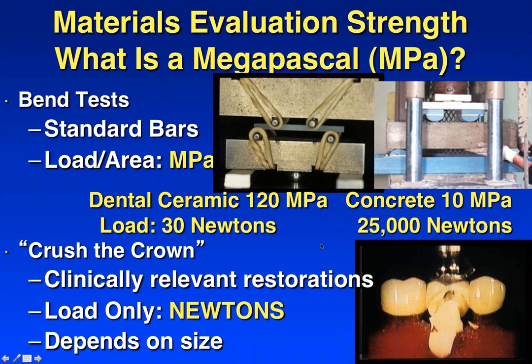What I think we really should be concerned about is load-bearing capacity, which is measured in newtons. When we make restorations, we make them the way we're going to use them in the mouth, the same thickness, the same geometry, as we're doing very complex things in the mouth with very complex structures. So we also do these load-bearing tests, and in my opinion, I really think that the load-bearing tests are becoming more important than the simple strength test, because if you look at this on a strength basis, you can be deceived very easily. So a dental ceramic is only 120 megapascals.